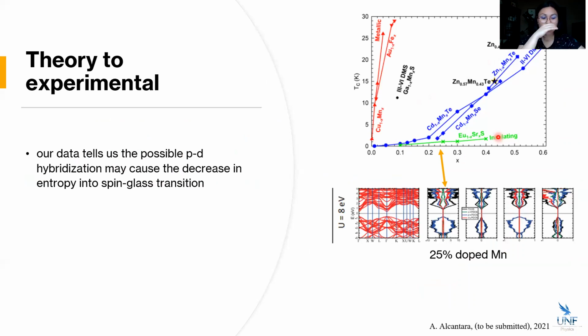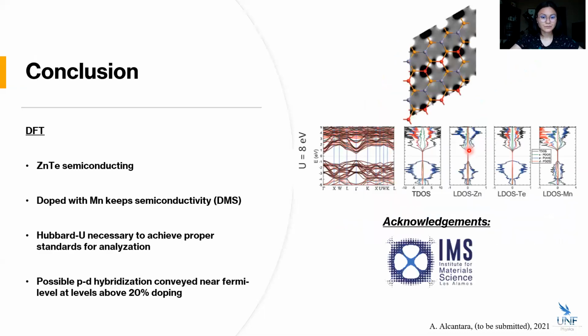So with our data, we wanted to assess the spin glass transition behavior in the experimental data. And if we look at the phase diagram, a shift in slope occurs around 20%, which tells us something is happening in the system. And so in our analysis, the system shows a weakening of the interaction between zinc and tellurium, and shifts to manganese and tellurium, essentially shutting out zinc. So we suspect what occurs is a shift in the electronic system, allowing these electrons to interact in the lattice.